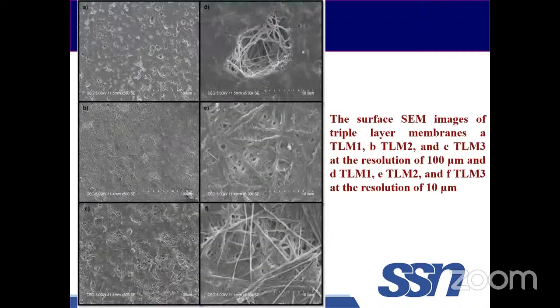So this is a typical SEM image of the 3 membranes that we prepared. This is the top layer, and this is the intermediate layer and the pores corresponding to the layer. As you can clearly see, as the PEG, the pore forming agent, continuously increases, the exposure of the intermediate layer is going to increase. It is getting increased, right?